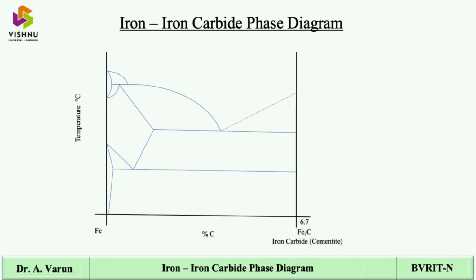Now this is the sequence of steps you need to remember in order to draw the iron carbide phase diagram. This is the only step that is to be remembered. When we discussed the pure iron temperatures, more or less the same temperatures will also follow in the iron carbide phase diagram. So it starts with 1539, then one intermediate which is 1492, then 1400, then another intermediate which is 1147, then 910, and now 723. These are the temperatures in degrees centigrade.